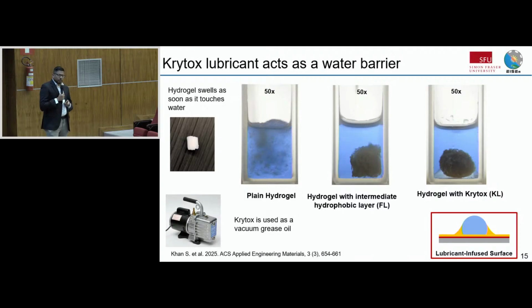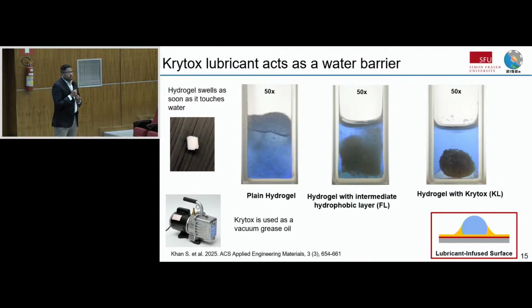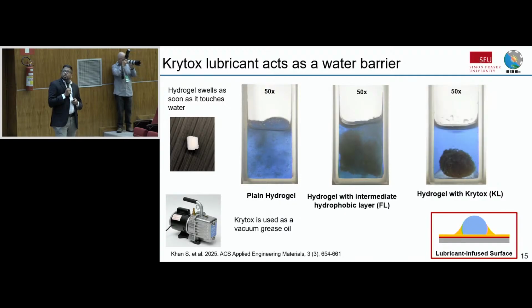So in the first one, you have a hydrogel. As soon as you put it in water, it swells to many times its own volume. In the second video, that hydrogel is coated with a hydrophobic layer. The hydrophobic layer is Teflon. And you would expect that it would survive in the water, but it's also swelling, right? And a good example of that is your cooking pan. If you have a Teflon layer, and if it has a crack or a scratch, then the cooking pan is not going to work, right? So solid coatings have that issue. In the third video, which I promise you is running, there's nothing happening, right?